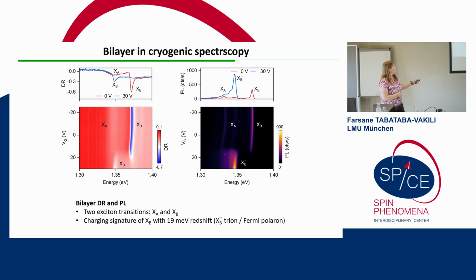And then at around 20 meV blue shift, we observe a very strong excitonic resonance, which we label here as XB. And then as we apply a gate voltage, XB becomes weaker and transfers its oscillator strength to a negative trion or Fermi-polaron here at around 19 meV redshift. So this is an exciton plus another electron. And we observe the same thing in photoluminescence.